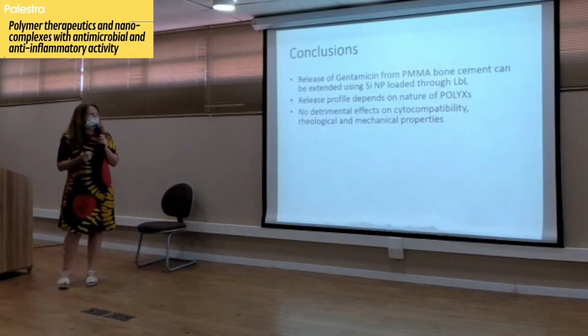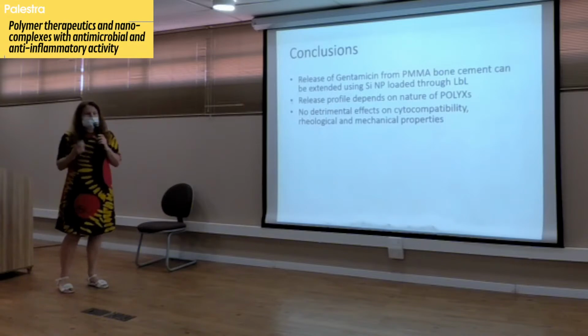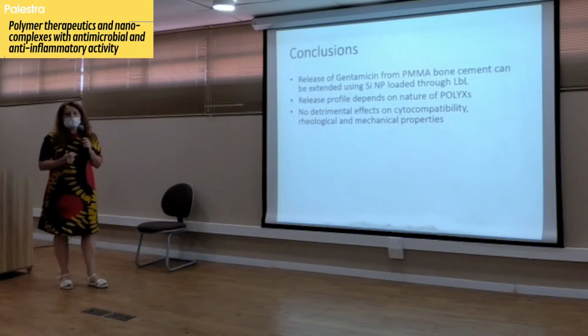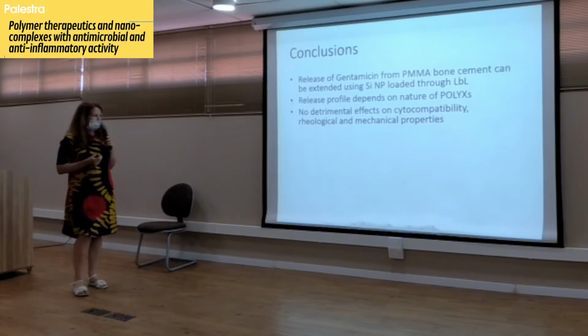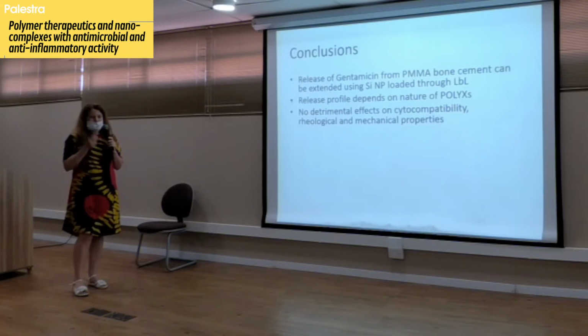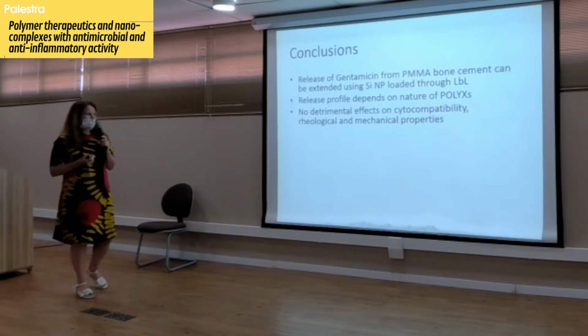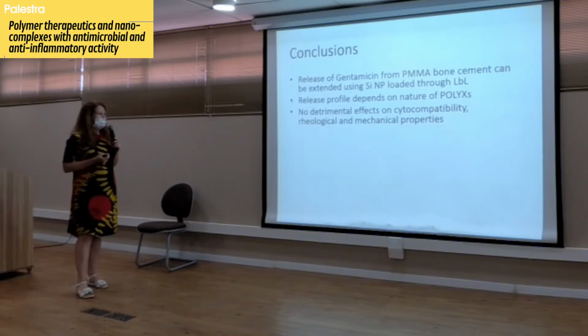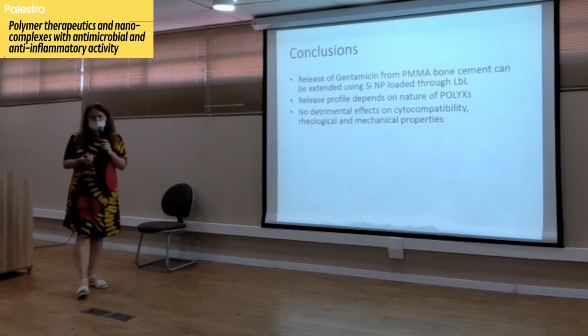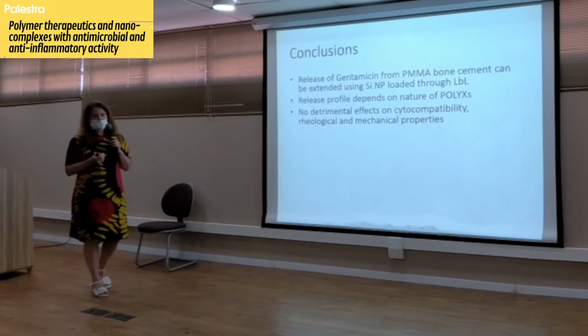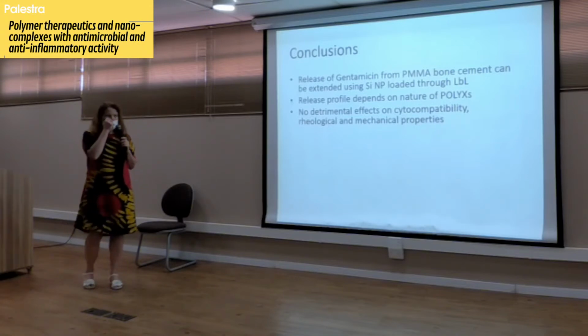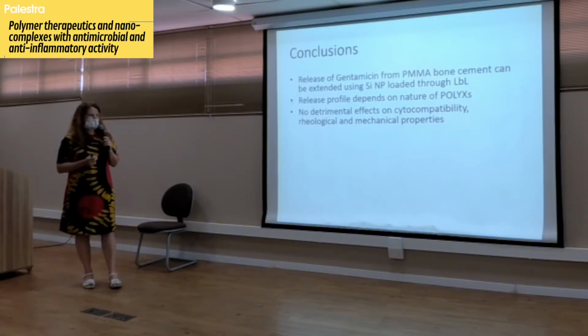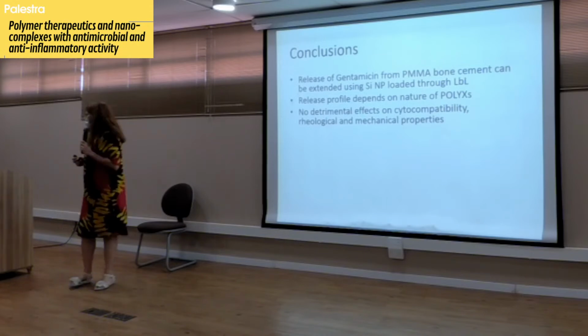So in conclusion, release of gentamicin from PMMA bone cement can be extended using silica nanoparticles, as has been shown above, using the layer-by-layer deposition technique. And this release depends on the layer-by-layer construct, and on the nature of the polyelectrolyte used as well. So we did not show any detrimental effect of the newly developed materials on cytocompatibility, mechanical strengths, or rheological properties.